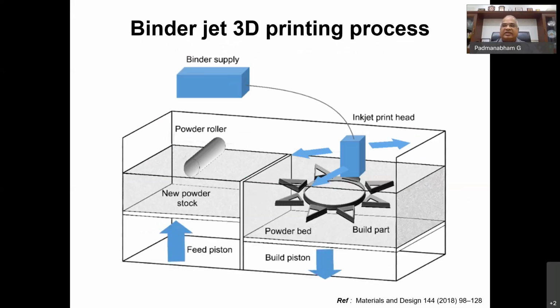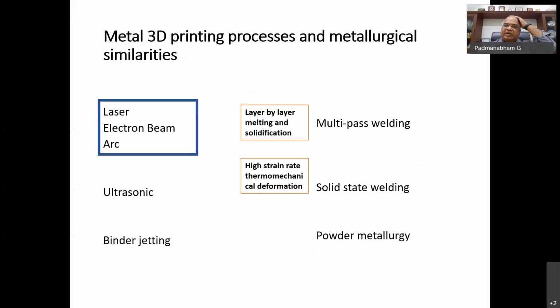And the next technique is, we don't use a heat source. We don't melt and solidify material. Here we use certain binders to form the shapes. The technique of having a bed and lowering the bed layer after layer is constant. But in that given layer, formation of the shape that you're looking for is by jetting certain binder, which solidifies, dries up there and gives you a green shape and then gives you the component. So we have to keep this in mind.